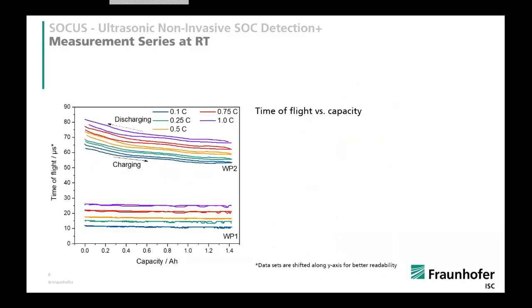One example is shown here in this graph, where the time of flight for the 2 wave packages, 1 and 2, are plotted over the capacity of the cell. And what you actually see is that wave package 1 in the lower half of the graph is nearly unaltered. You only have a time of flight change of approximately 6%. Wave package 2 changes quite substantially, about 20%. A small side remark, of course, all these measurements lie on top of each other, so for the sake of readability we shifted them on the y-axis.